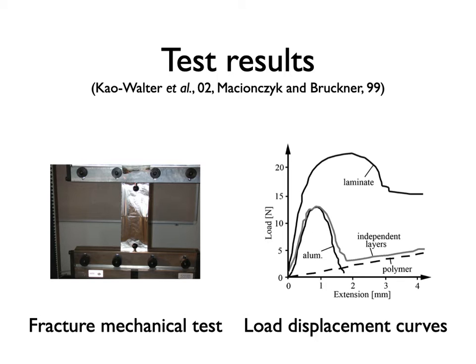But when you add these two layers together, you get the laminate curve, and you see it's much, much bigger. It reaches almost twice as high peak load, and also the absorbed energy, which is the area under the curve, is enormous compared to what you would expect these two materials to contribute with. So that's the interest, but the focus now is on the buckling of the foil.